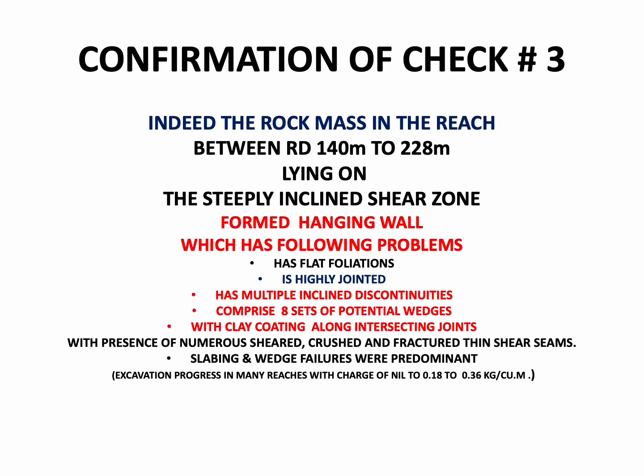So the third confirmation check also is proved true, that indeed the rock mass in the reach between RD 140 to 228 meter was lying on the steeply inclined shear zone. It formed hanging wall which has the following problems: has flat foliations, is highly jointed, has multiple inclined discontinuities. It comprises 8 sets of potential wedges with clay coating along the intersecting joints, with presence of numerous sheared, crushed and fractured thin shear seams. Slabbing and wedge failures were predominant because of their orientation becoming less than friction angle.